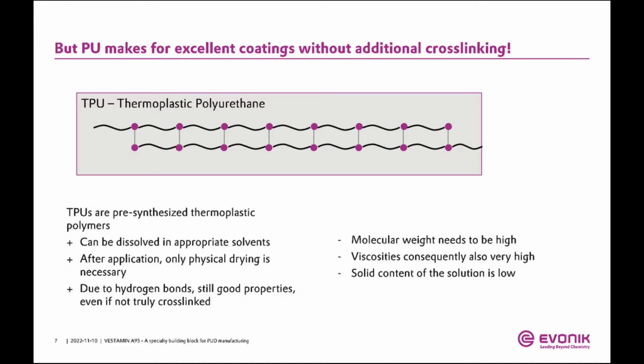they form these interlinkages, like these hydrogen bonds, that cause these relatively good and decent properties, even if they are not truly three-dimensionally cross-linked by, let's say, typical chemical bonds. So that means we can make thermoplastic polyurethanes and have them applied as a coating, and then just apply them and don't cross-link them anymore, don't have a curing mechanism anymore. That means after the application, we only need physical drying, right?